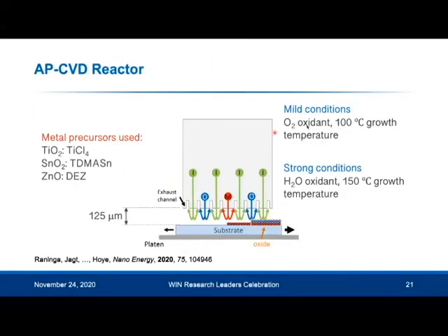And here is the setup for my APCVD reactor. And here you can see the metal precursors. So that's in this red channel here for the three different oxides. And I'm mainly comparing two different growth conditions. I'm comparing what I call mild conditions, which is where I'm using oxygen gas as the oxidant. And this is less reactive to the perovskite.